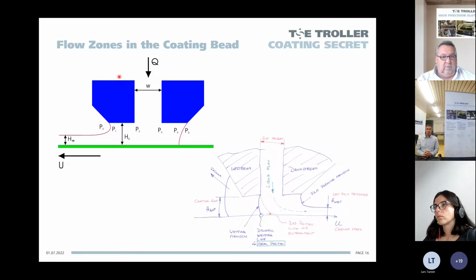Here you see the flow zones in the coating bead. Again, here are the pressure indications, and a picture which is unfortunately in the opposite direction. So here the web runs to the right, here it runs to the left. But this is just to explain the definitions again. And here you see, for example, this red dashed line. This shows a bad position of the dynamic wetting line, because then you have air entrainment from the backside. You can get air bubbles between the liquid and the substrate, and then you have a bad coating result.